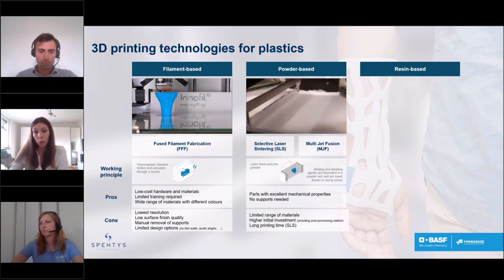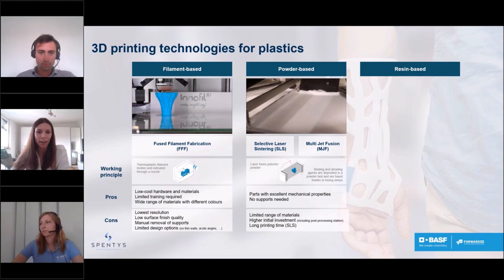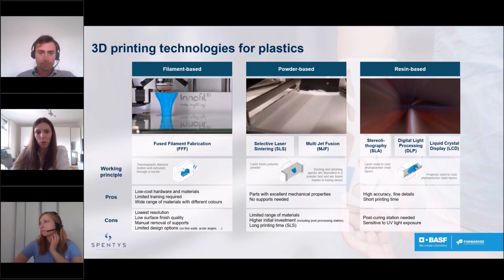For most applications the benefits of FFF outweigh the cons. The second technology is powder-based, where material is fused by an energy source such as a laser or lamp. This includes Selective Laser Sintering (SLS) and Multi Jet Fusion (MJF), which share similar pros and cons. The main advantages are excellent mechanical properties and no support structures needed, since the part is printed within a powder bed. Compared to FFF, fewer materials are available and the initial investment is higher, but for applications like prosthetic sockets the advantages are significant.